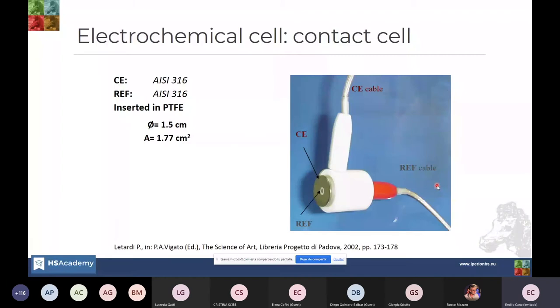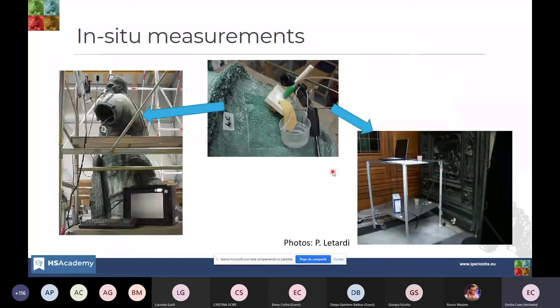This is a small cylinder embedded in holders, with connections for the cables. They are made of AISI 316 stainless steel. This small circle in the middle acts as a reference electrode. The outside ring, the outside bottom of the cylinder exposed to the metal, is the counter electrode. And she covered it with this cloth. By keeping the tail of this cloth immersed in a vessel containing the electrolyte, you can keep a wet surface and apply it to the surface of the sculpture or the real work of art we want to measure.